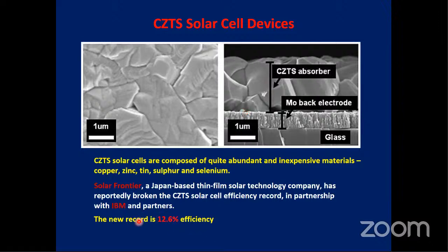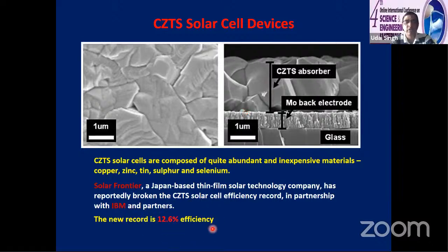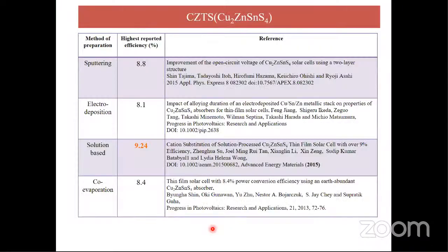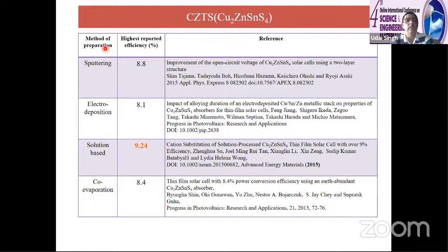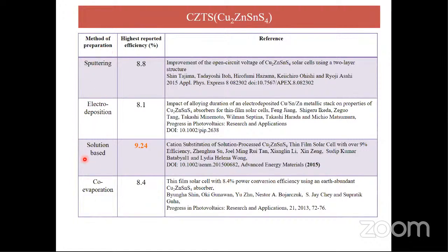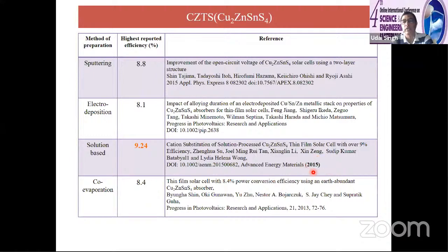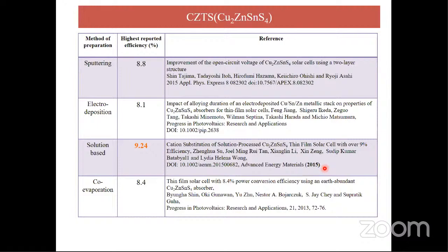So the highest efficiency achieved is only 12.6, and that is only on the lab scale. This is for the CZTS material. You can see people have used different methods, and solution-based has given 9.24 efficiency, that is also in 2015. So no increase in the efficiency for 6 years in this material, copper zinc tin.